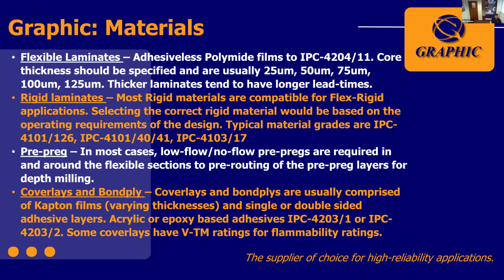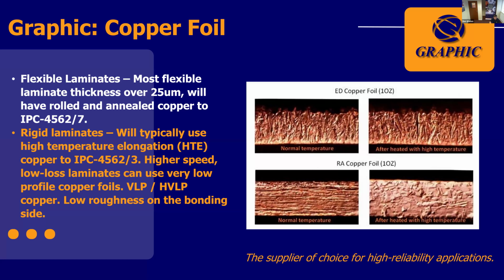Okay, so moving across now to the copper foils, and in particular, what we're going to be talking about today is the copper foils on flex rigids. So flexible laminates, at Graphic, we always like to work with rolled and annealed copper. There are flexible laminates out there that have electrodeposited copper, but as you can see from the pictures on the right-hand side, the rolled and annealed copper has an in-plane grain direction. So a direction of the copper grain, effectively, which makes it brilliant for flex rigids in particular.